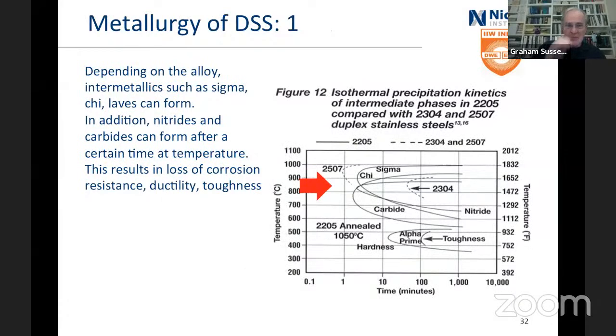Okay, a bit about metallurgy. You can get the intermetallics, sigma phase, chi, Laves, etc. Don't worry about what they are. It means that they're intermetallics, so the things that should be giving you corrosion resistance are tied up with each other, so they don't make the chromium oxide film. The other snag is that you can get nitrides, carbides, not so much if you've got impurities around, but there's not an awful lot of carbon in the duplex stainless steels. But if you heat it for a long enough time, yes. And all of those mean that the corrosion resistance goes down, the ductility and toughness change.